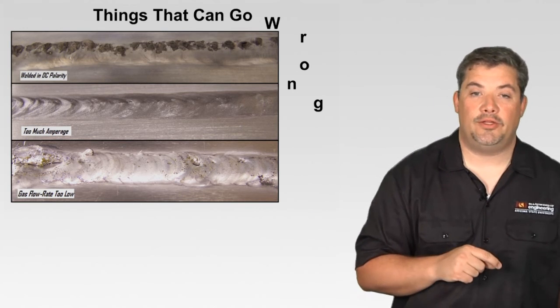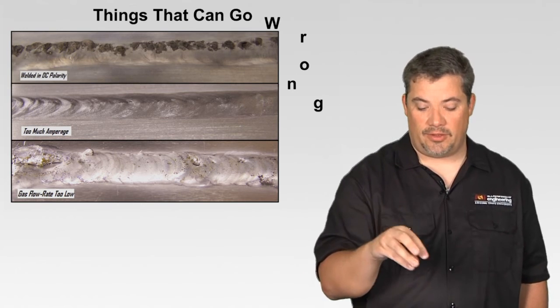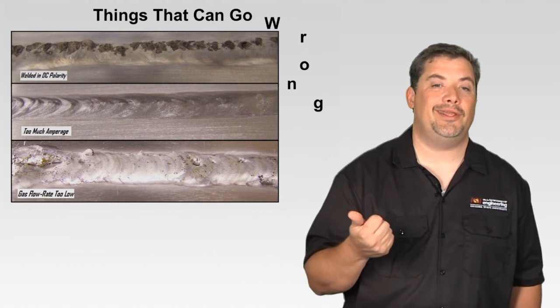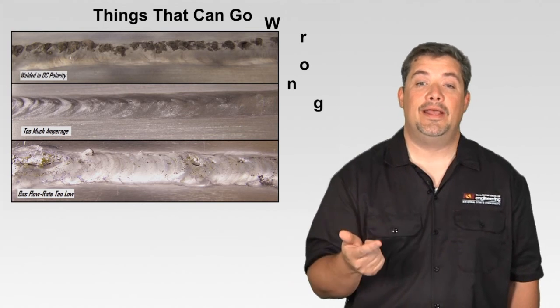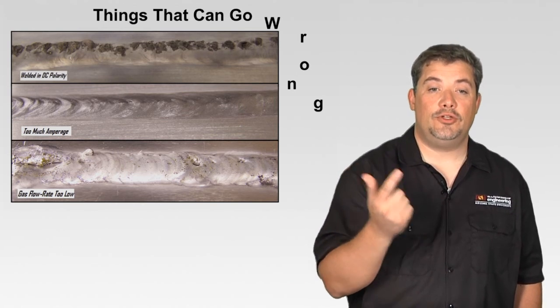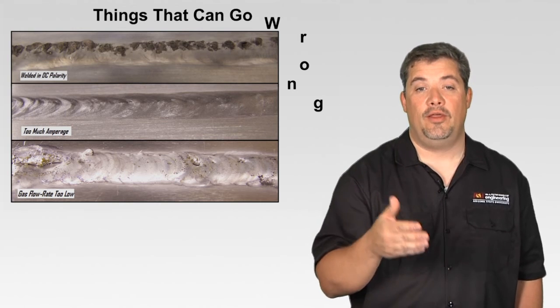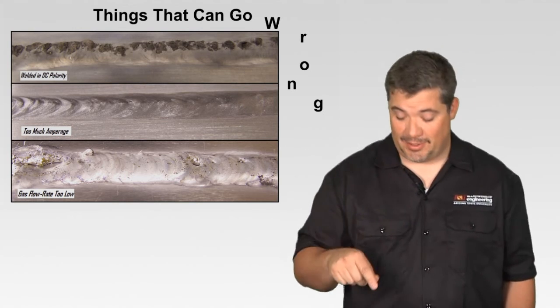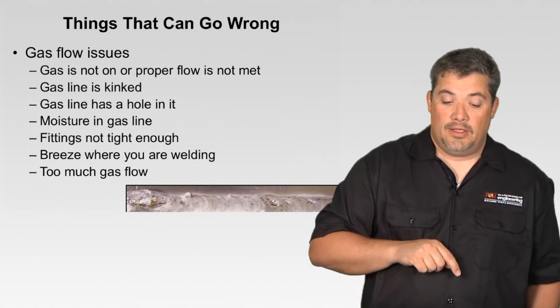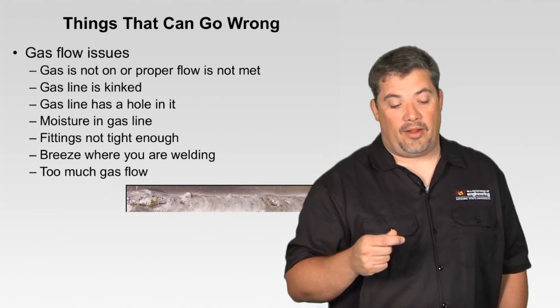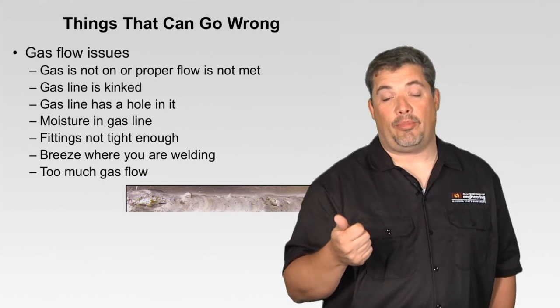The gas flow rate is too low at the bottom; you can see there are little speckles all over the surface. That could be contamination of the gas or a lack of gas, but either way, too low a gas flow, or not enough argon in this case, is a bad thing. So the gas flow issue may be that the gas is not on or the proper flow is not met.